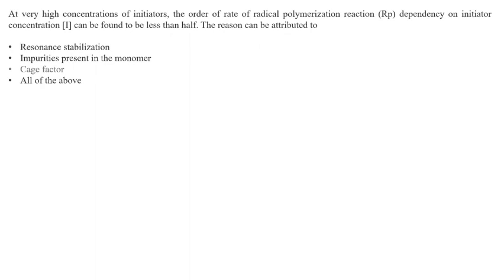At very high concentration of initiators, the order of the rate of radical polymerization, Rp, dependency on initiator concentration can be found to be less than half. The reason can be attributed to: there are three reasons listed here. First is the resonance stabilization, impurities present in the monomer, and cage factor. Resonance effect occurs only when the functional group present is causing some sort of charge distribution, and because of that the resonance stabilization will occur. But that has no role in the order of rate of radical polymerization reaction. And impurities present in the monomer are not going to help it either. But cage factor can be a thing. What is cage factor?